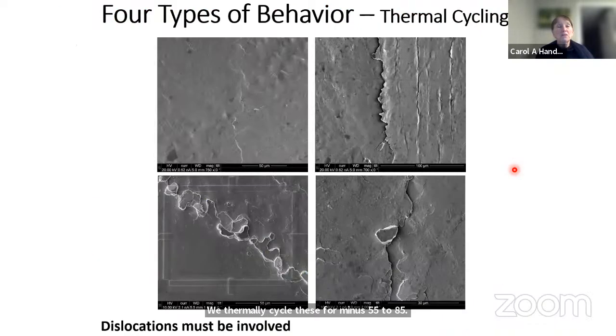And so what we saw was near the grain boundaries, we would form whiskers. We had regions that completely recrystallized. There was grain boundary sliding. And I'm not going to be able to share with you all the different components of this. But one of the things that we realized by moving to the bicrystal films, and initially for these grains, there is a single orientation all the way up to the grain boundary, is that because we're nucleating new grains, the dislocations must somehow be involved.